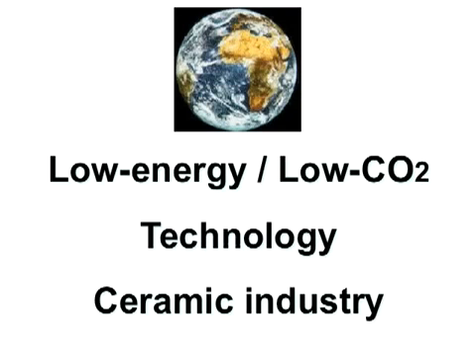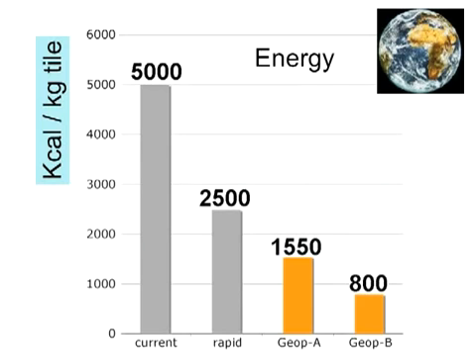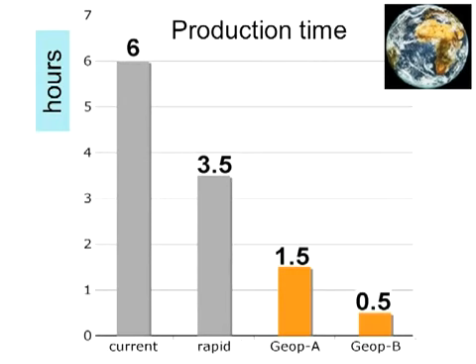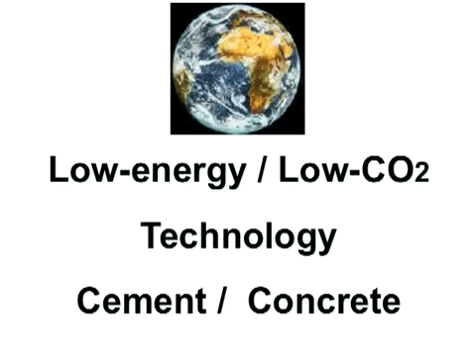One of the major results, we had several posters, but one which is really striking is the following one. Low energy, low CO2 technology for the ceramic industry. If you look at the energy consumed to make a tile with the geopolymer chemistry, you divide the energy by 3 or 6. If you look at the production time of a ceramic tile using geopolymer chemistry, you divide this time by 4 or by 12.